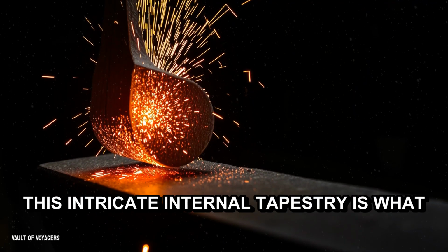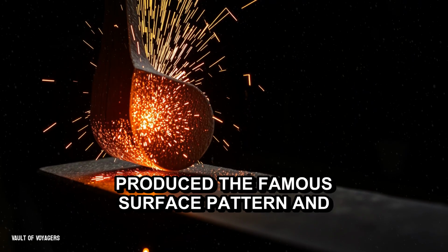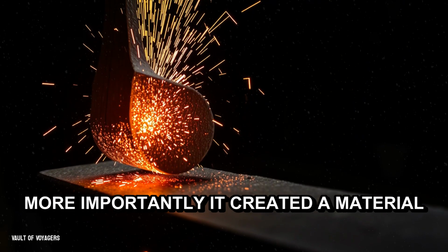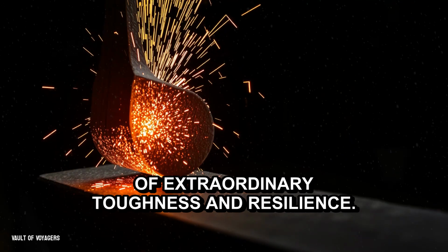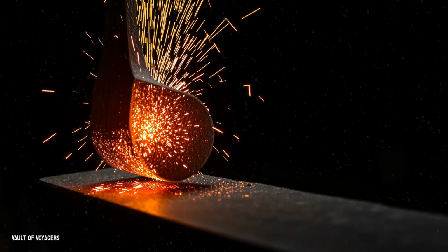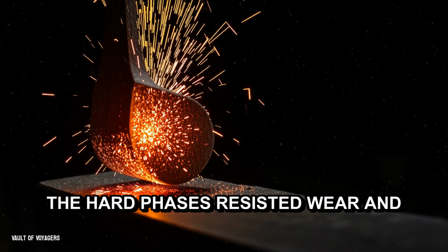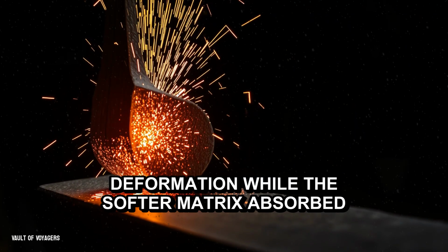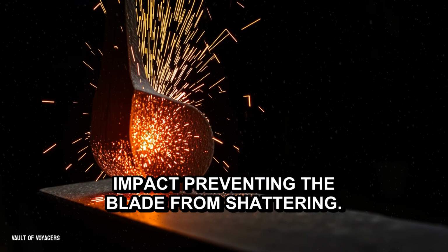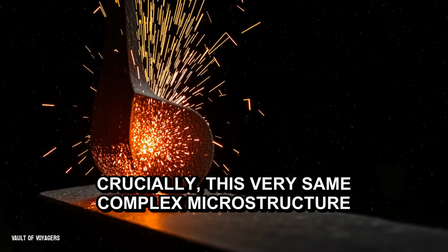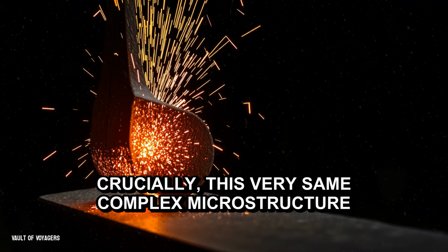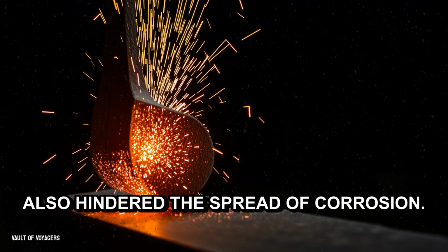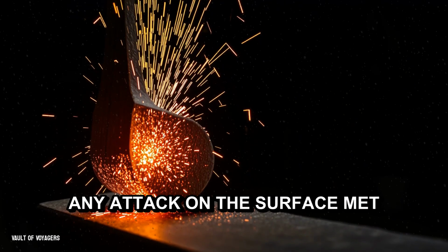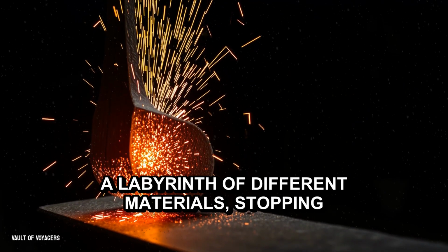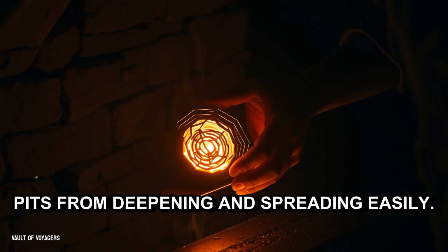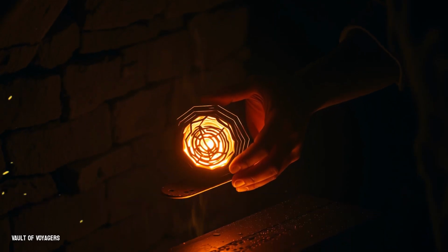This intricate internal tapestry is what produced the famous surface pattern, and more importantly, it created a material of extraordinary toughness and resilience. The hard phases resisted wear and deformation, while the softer matrix absorbed impact, preventing the blade from shattering. Crucially, this very same complex microstructure also hindered the spread of corrosion. Any attack on the surface met a labyrinth of different materials, stopping pits from deepening and spreading easily.